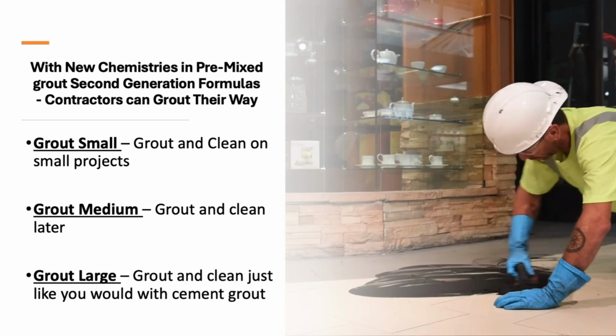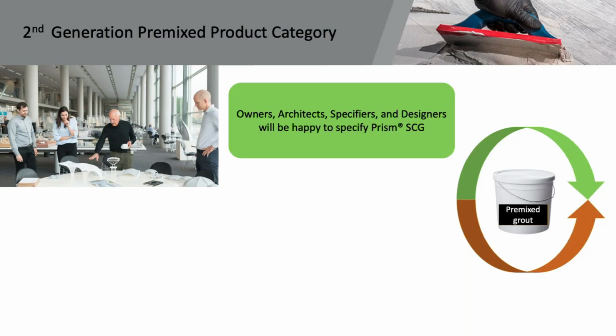Okay, with the second generation premix, we were able to find out you could grout small areas, medium areas, or large areas. And the installer did not have to change. So now anybody that knows how to do a cement-based grout installation can do a premix grout installation, and it's going to work the same way with coming back and cleaning the grout off at a reasonable amount of time. It's able to stay on the grout tile longer than the first generation.